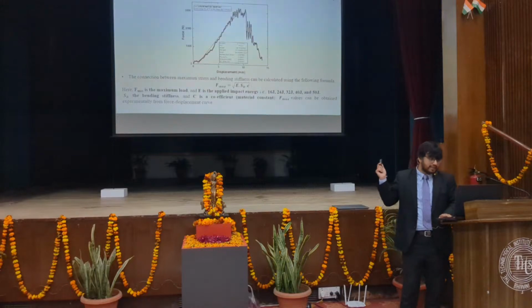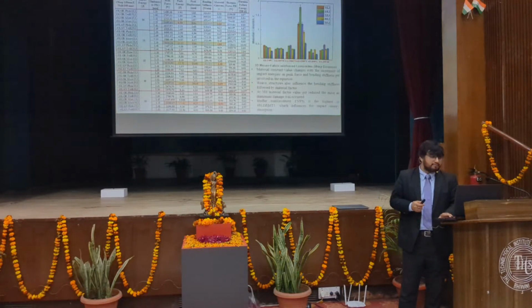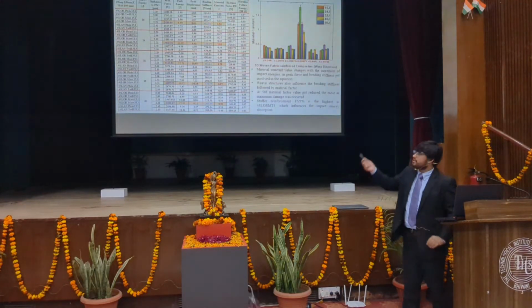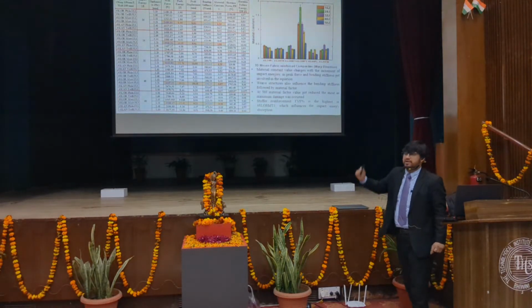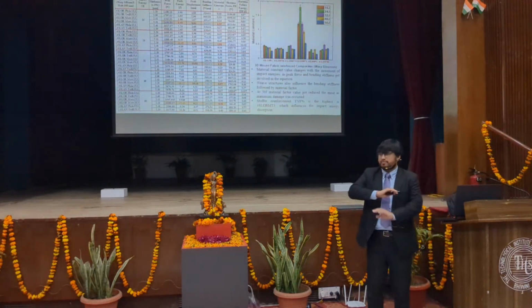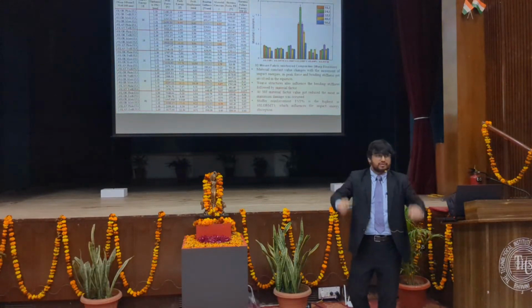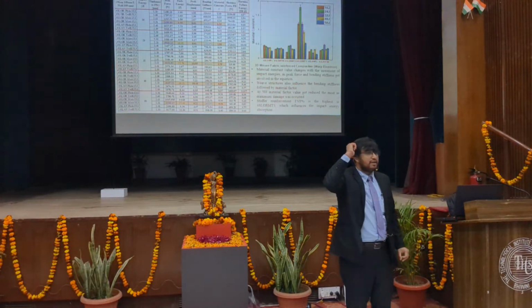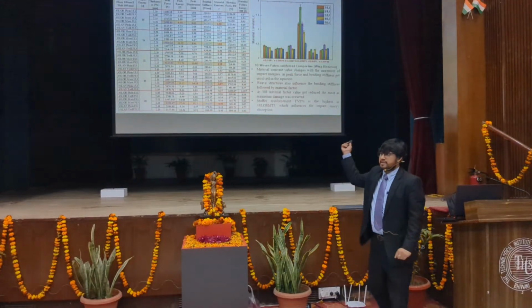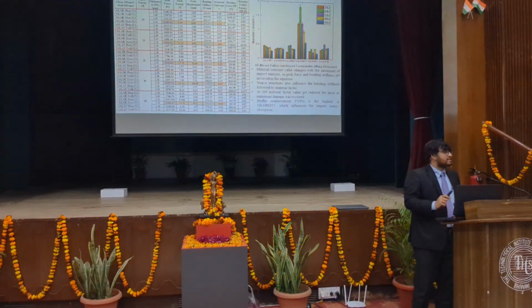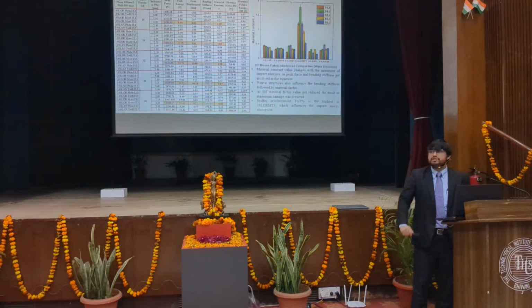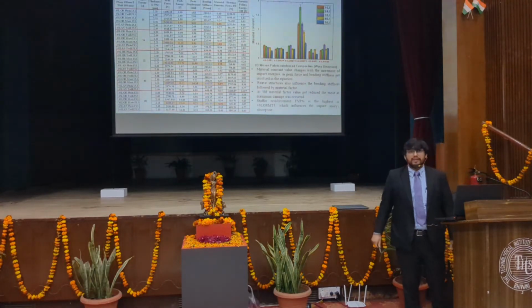I already explained how to calculate the bending stiffness here. And from the material constant value, you can also see the basket structure among all kinds of structures. Let's forget about whatever I told you of different structures, but there is one structure that showed its high peak, and that is the basket structure. From the high peak, you can understand that basket structures have a very superior ability for energy absorption than any of the other structures. So for the industry, we need to tell them that, look, you should make some basket structures instead of these conventional plain or twill structures.